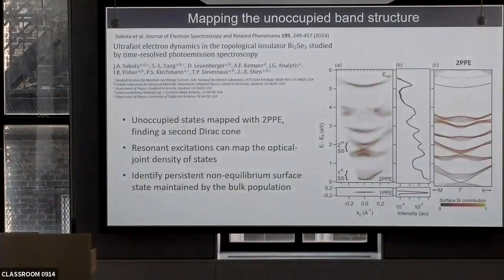Another example, or another way of using this beautiful data coming from the exchange group, where basically you're doing a two-photon photoemission experiment. You're looking at a topological insulator, bismuth selenide in this case. Here is the chemical potential. So with standard photoemission, you would look at electrons below, so the occupied states. But what is being done here is to excite electrons from the occupied into the unoccupied electronic structure, and then photoemitting them from there. So pretty much what you're getting is a picture or a mapping here of the unoccupied